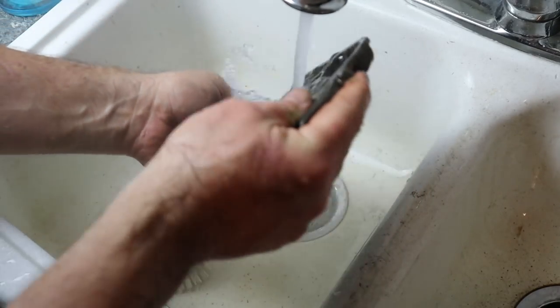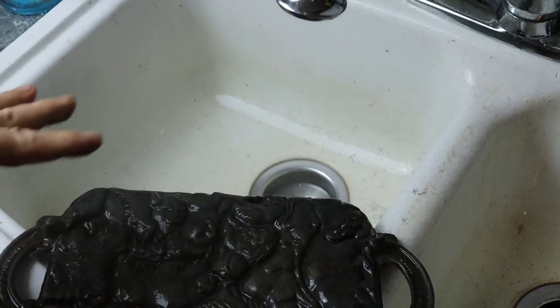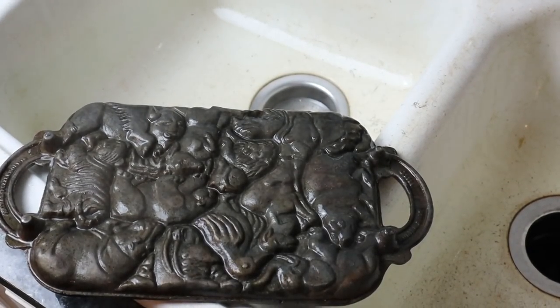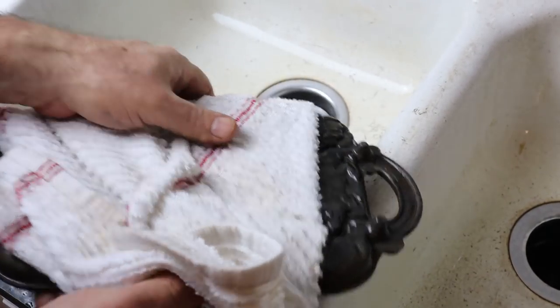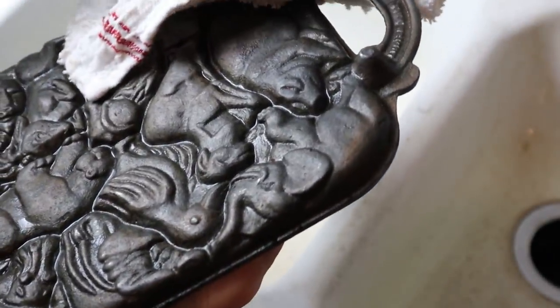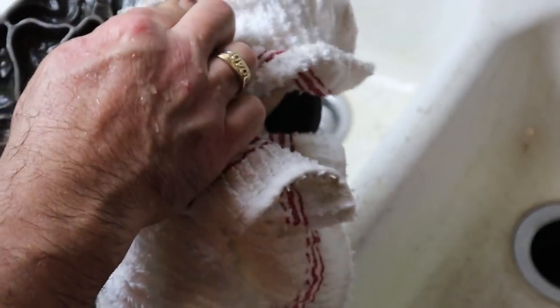I like to rinse it with as hot of water as I can stand. A lot of people like to rinse with cold and say it stops the flash rust, but I rinse with hot water so it'll dry quickly. You dry it off really quick with a towel — you don't have to get it bone dry, because we want to stop the flash rust. So we're going to dry it off quickly, and along with the pan being hot, it'll evaporate really fast. Before the flash rust has a chance to take hold, we'll go ahead and apply a layer of seasoning.